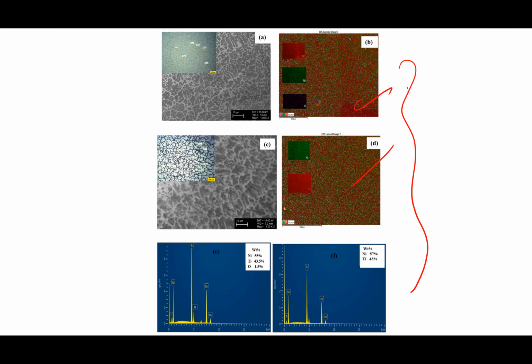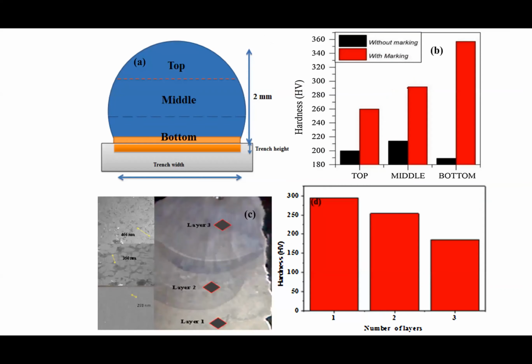So if I try to observe the average hardness, the average microhardness of the single track of the VAM deposited NiTi varies in the range of 200 HV to 350 HV, and it can be seen that the hardness of the bottom section is higher than the middle section and the top section. So the laser marking provides a larger cooling rate due to its large surface area and a high heat flow to the surface, and the middle section and the top section revealed a low cooling rate because of the low temperature gradient in the melt pool.